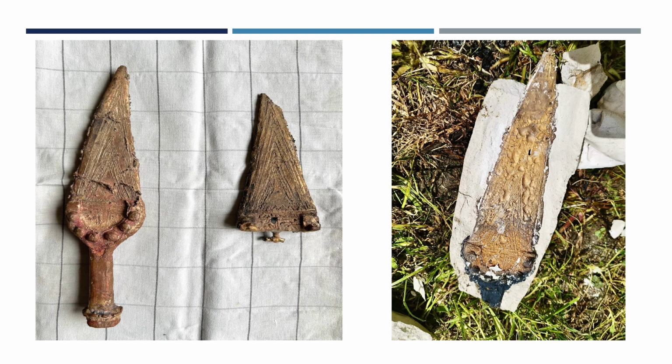The first 2 were somewhat successful, but the one on the far right is definitely the most complete in terms of visible decorations. The 2 on the left were from the daggers I had made previously, and I had incised far too deeply into the wax, and you can see that the decorations are not as fine as on the original object. The dagger on the far right,